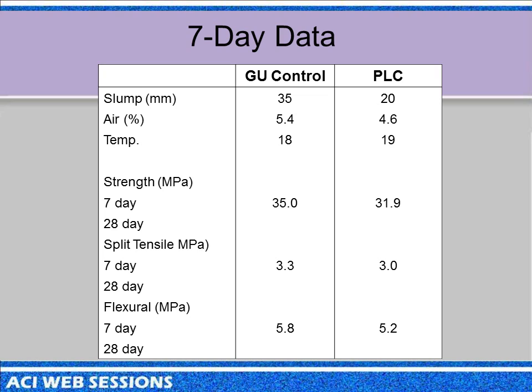They're looking at about 1-inch slump, 1.5, about 5% air. It was about 65 degrees temperature in the concrete. The weather outside was a bit cooler. The 7-day strength of the limestone mix was lower on this truckload versus that truckload, and the split tensiles sort of reflect that, and the flexurals at 7 days. If this talk was a week later, I'd have the 28-day data.